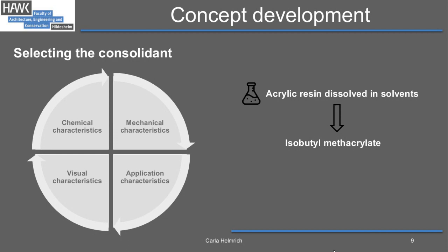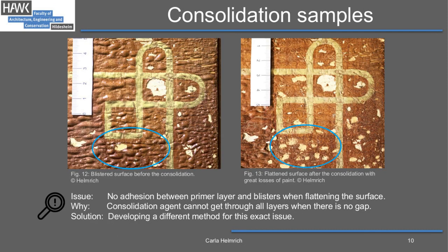During sampling, it became clear that applying the agent with a brush alone was not suitable for all blistered areas. This was particularly noticeable in the case of blisters that were attached to each other or had no stomata or defects in the surrounding area, as you can see in this part of the photo. The problem was that the agent could not get into all the layers. As you can see in figure 13 here, there was a major loss of paint during the flattening process of the blisters. Hence, two different methods had to be developed for applying the agent.